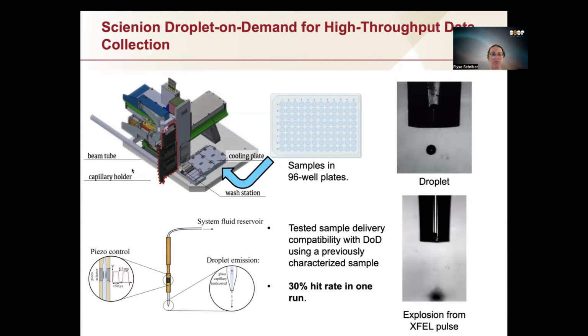What makes the Scienion droplet on demand so unique is that we have a 96-well plate that can be placed inside a cooling plate, and we have a robot that can actually move the nozzle, which is controlled via piezo actuator. It can pull up sample at a specific volume, and then using this piezo actuator system, it can emit droplets that are perfect, that are the exact same shape and the exact same volume. And it can be synchronized perfectly to the X-ray pulse delivery, so anywhere from 120 hertz to 10 kilohertz.